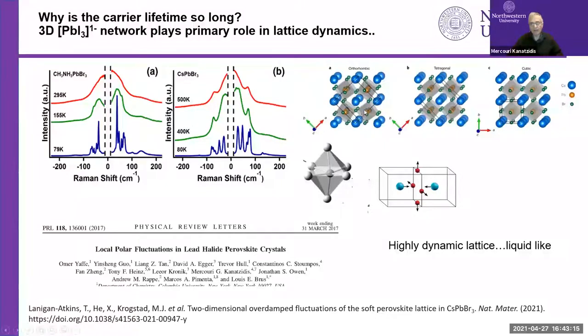And the way this happens is the octahedra rotate, the metal, which is at the center of the octahedron, goes off center, and the cesium, which is in a cage, also goes off center. So it's very dynamic at room temperature, and I believe because of that, when we make electrons and holes, they get lost and they cannot find each other soon enough to recombine. And that lengthens the lifetime, and therefore we have a chance to collect the signal.